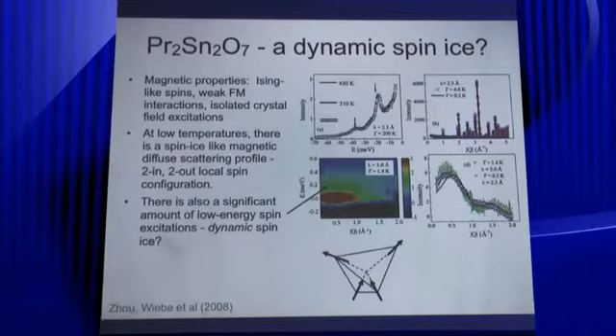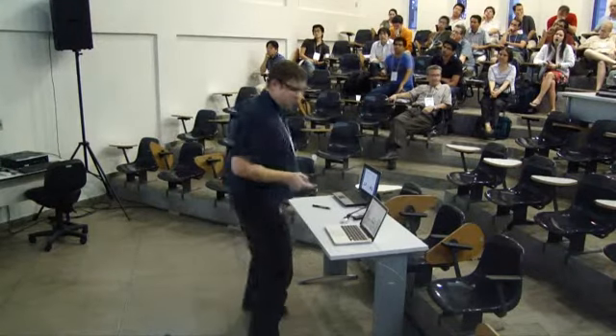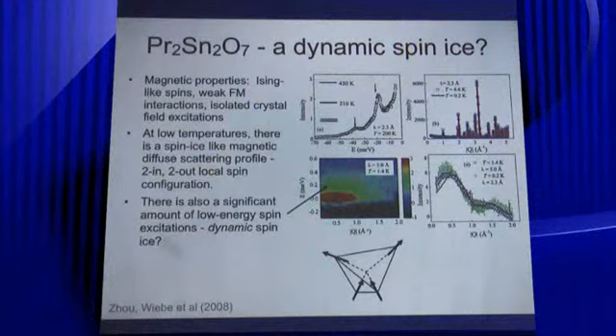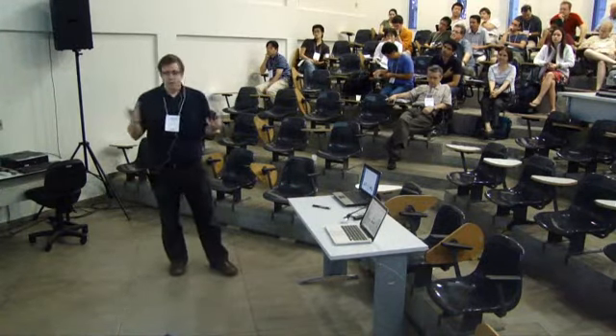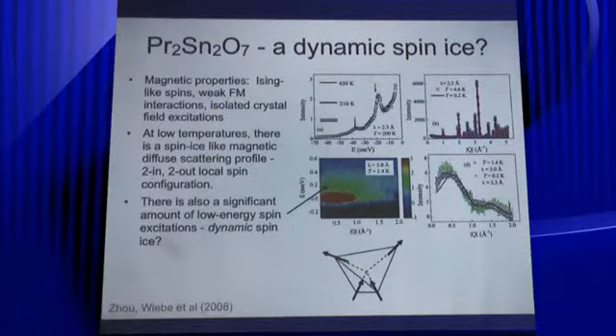The surprising thing for us was looking at the inelastic spectrum, where we noticed that there was a lot of spin fluctuations at low temperatures. So this is very different from spin ices, which are basically static on the time scale of this time of flight measurement. So the idea we had was that locally you had this 2-in, 2-out configuration in each tetrahedron, but you had some sort of spin fluctuations at low temperatures, which could possibly be some sort of tunneling between different states.